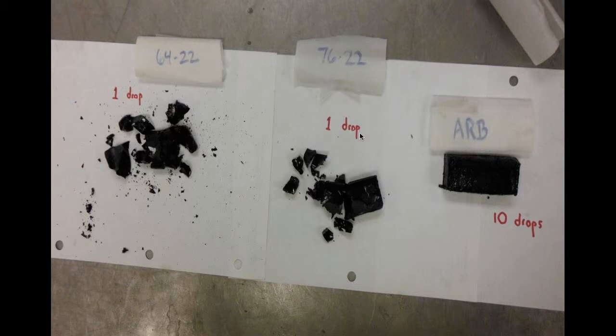6422, a 30-gram specimen. I believe they were 30-gram specimens. These were all like size specimens. And I used a test hammer that we use in the laboratory. I dropped one drop. These were cooled to, I think, 35 degrees, 35 to 38, all the same temperature. One drop on the 6422, you can see how far it shattered. 7622, the more expensive, you can see it didn't break down quite as much.